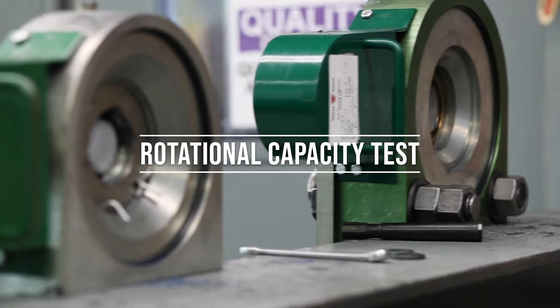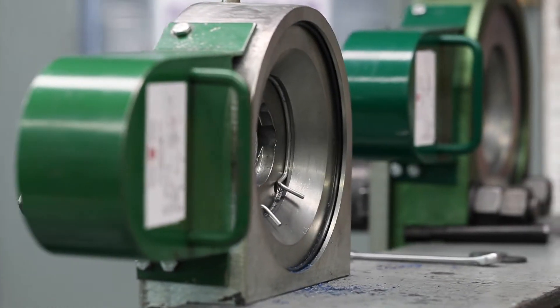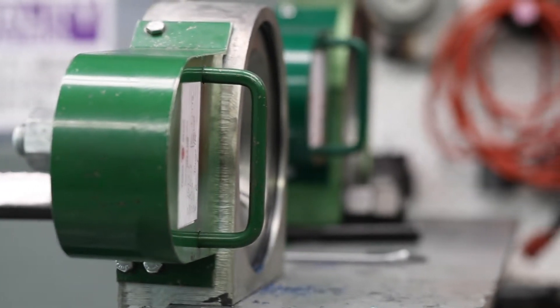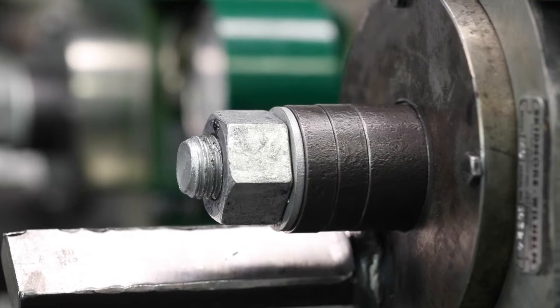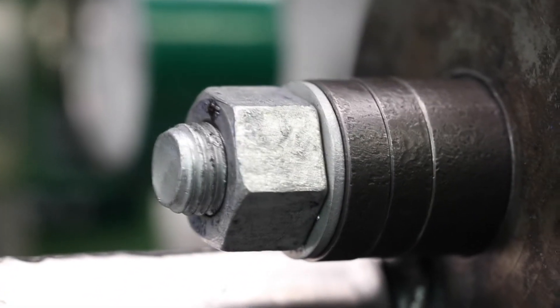Rotational capacity, or RC tests, are intended to evaluate the presence of lubricant, the efficiency of lubricant, and the compatibility of assemblies. The test serves as a further quality control measure against excessively overtapped nuts and material with insufficient ductility.